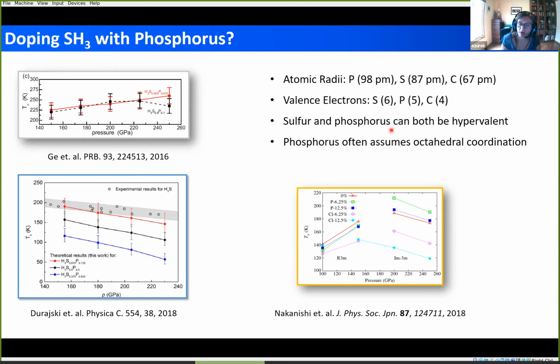But sulfur and phosphorus can be hypervalent, and phosphorus is often going to assume octahedral coordination. So we would expect that these octahedrally coordinated systems that I previously discussed, which are not very stable within DFT 0 Kelvin type calculations, would be potentially more preferred.